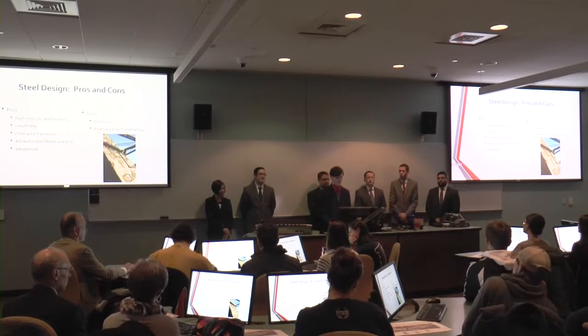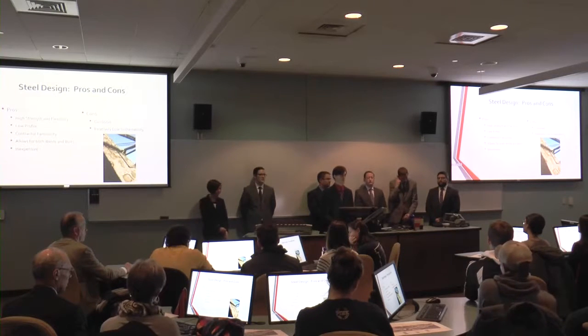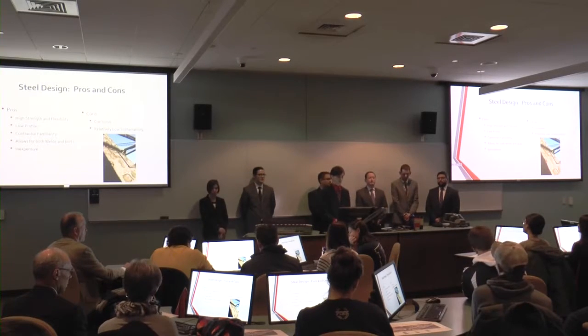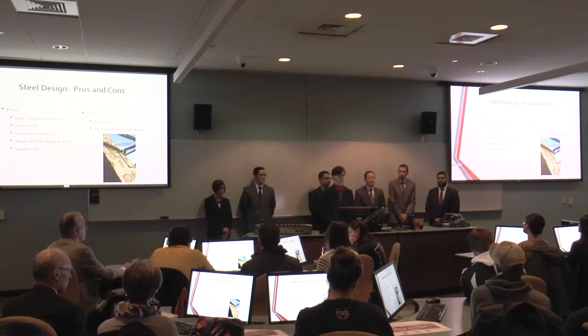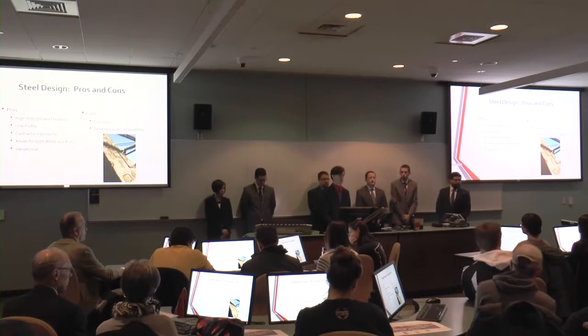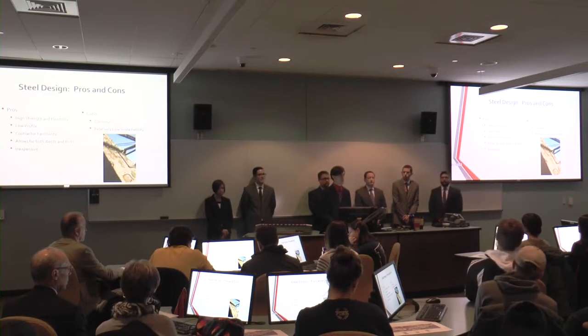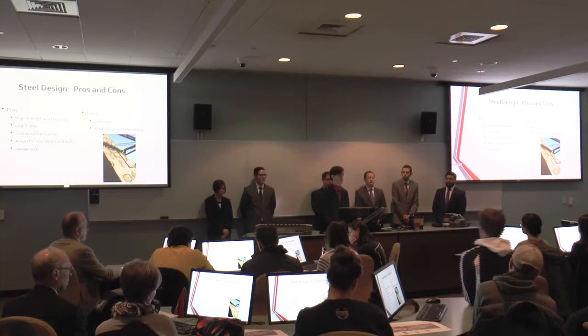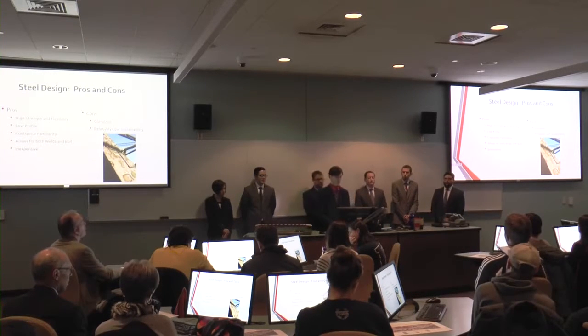So we looked at originally using weathering steel, thinking, if the weathering steel doesn't really corrode, you don't lose a substantial amount of section, then it'll maintain the same strength. However, at the beginning when you first put it in, the weathering steel does still corrode and rust will end up falling into the stream, which is generally a bad thing.